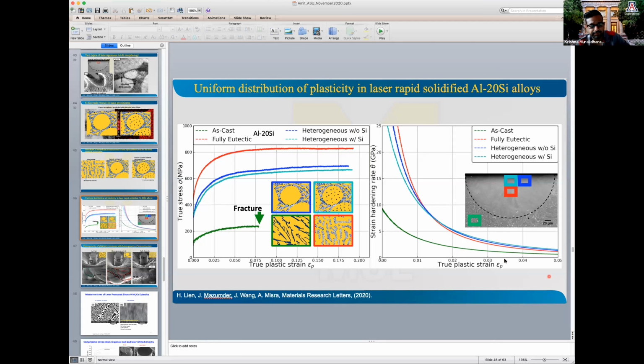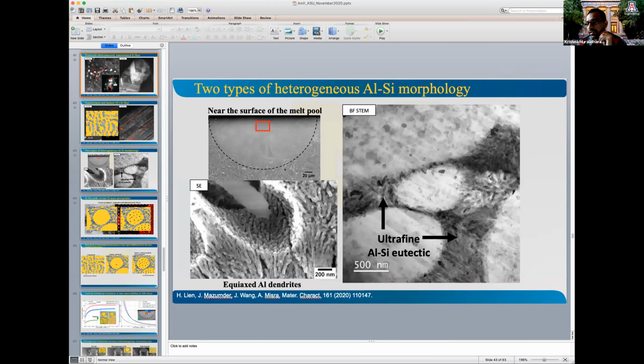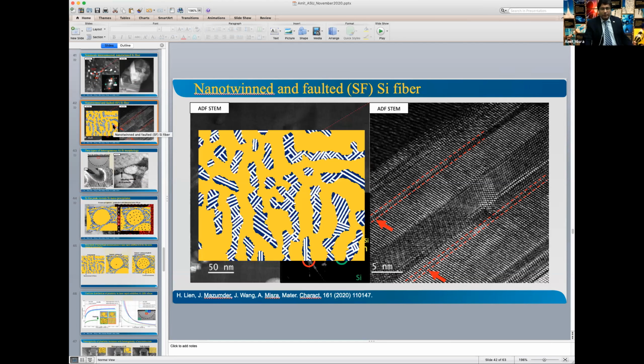I had to take a quick call. When you were discussing the aluminum-silicon, you said that in the silicon you were seeing twinning. On load application or release, is there a chance of detwinning in silicon at all? So this is twinning from growth. It's not from deformation. It's a growth twin.